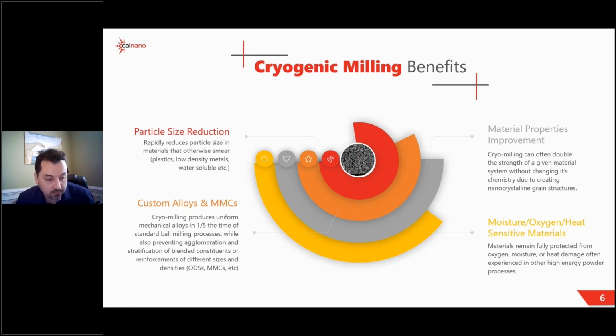And beyond the ability to mix materials you could normally do in a melt, we have the additional benefit of not being limited by certain limiting factors. For instance, if you try to historically melt or add a very low melting point and low vaporization point material, zinc is an example, into an alloy system that is based on a much higher melting point material, you can have the low melting point and vaporization point material vaporizing before it can even be alloyed with the materials that haven't even liquefied yet, causing a lot of limitations.